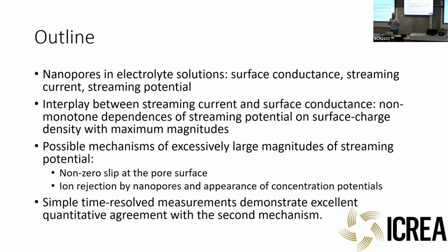The mechanisms may be various: it might be preferential adsorption of either anions or cations, more frequently anions. It might be dissociation of the so-called ionogenic groups, which in a dry state are neutral, and then in water, hydrogen, for example, splits off, and there is a negative charge remaining.